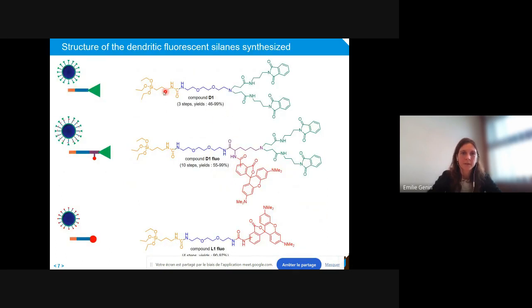So the different ligands that we synthesize are shown here, and each was synthesized in 3 to 10 steps with quite good yields, and all of them bear triethoxysilylated anchoring groups to graft onto the titanium surfaces.